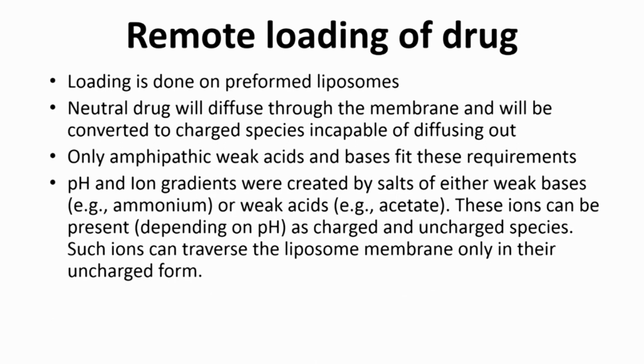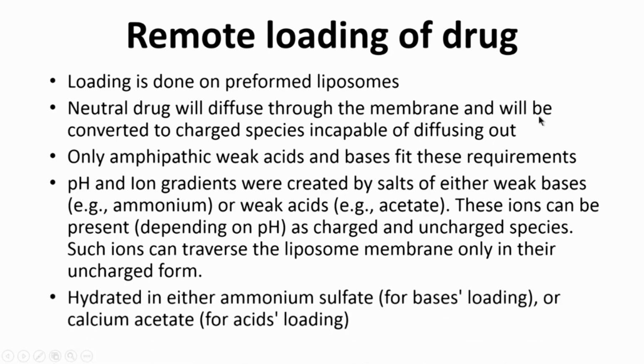Then a pH and an ion gradient is created. This could be done by using weak bases like ammonium or weak acids like acetate, and depending on what the pH is inside or outside they can be charged or uncharged, and that is how they can traverse through the liposome membrane only in their uncharged form, and we will explain how this actually happens. So, these empty liposomes are not really empty liposomes, but they carry these salts.